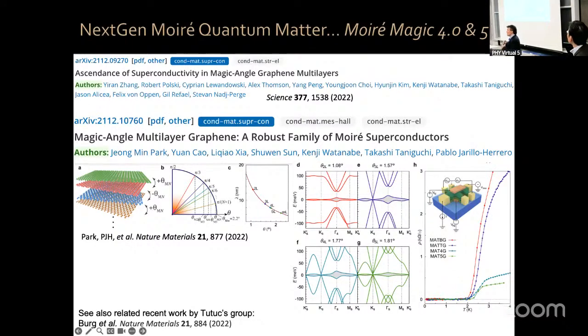So it's not like we get much closer, much stronger interactions, and a much higher energy scale by going to a larger number of layers. TC just increases, but it saturates to something of the order of 2 point something Kelvin. So a way to get to room temperature won't be to add more layers, at least within this simple model for how to generate flat bands as you keep adding layers.